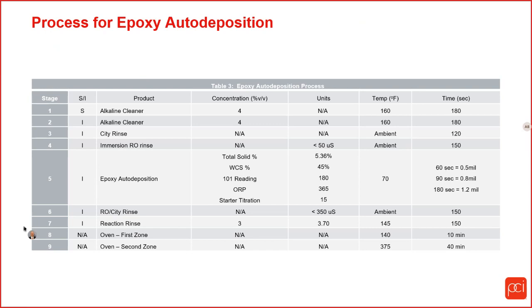After the epoxy auto deposition, it goes through another RO rinse and then a reaction rinse or a seal, as Steve said. There are 2 oven zones that we followed for this particular product. And the first one, like Steve said, was a dewatering zone. And the second one is a cure oven.